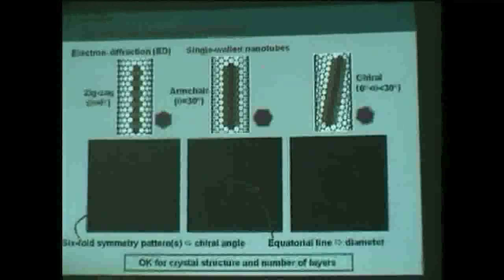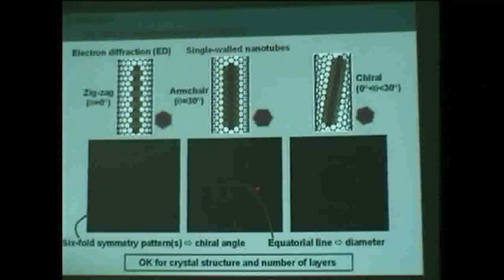For these three examples, the only thing which is different is the chiral angle. You can measure it - it's just the orientation of this hexagon compared to this line. You can easily measure this angle. In this case, you measure it twice, getting plus and minus this chiral angle, but these two hexagons are just symmetric compared to this plane. So with the orientation of this hexagon, you can measure the chiral angle.